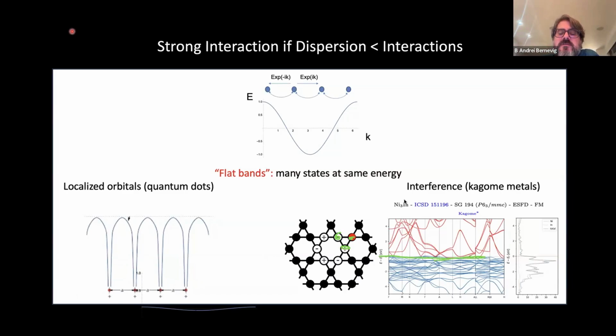This is a band structure of this material. This is how band structures basically look in nature. These are the allowed energy levels of this material. The reason why there are so many is that nickel has d orbitals, so 5 d orbitals times spin, so 10, but there are 3 nickel per unit cell, so you already have 30 orbitals, so at least 30 bands. So it becomes a spaghetti of bands, but you can clearly see that even though you have a spaghetti of bands, there are some bands which are basically flat, i.e. do not disperse